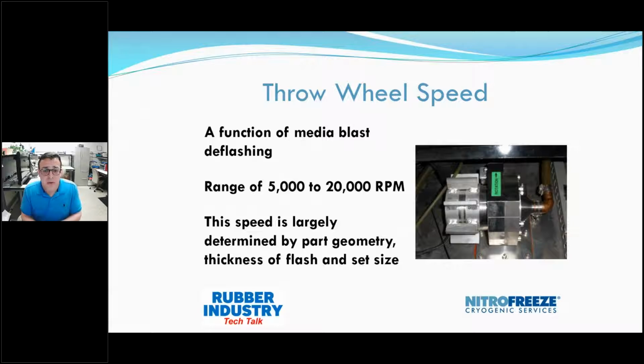Thickness of flash is going to matter tremendously here. If you've got a part with tear trim and the tear trim is several thousandths thick, yes, you have to run it at a higher speed. For thinner parts, I always recommend again going in the middle. With our machine in particular, you'd probably be sub 15,000. If you've got a thicker part with thicker flash, a larger part, you can go higher.